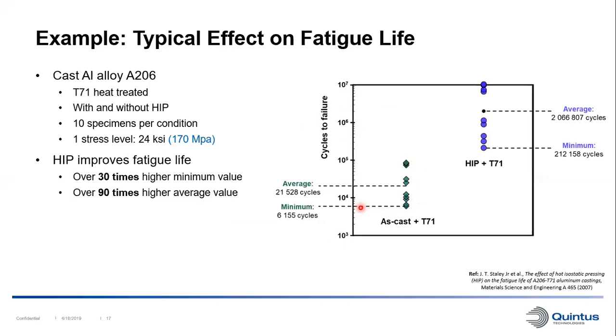Here we can see that the specimen that produced the minimum amount of cycles was around 6,000 cycles, and the average life was around 21 to 22,000 cycles. On the right here in blue, we have the same material that's been HIPed and then T71 treated. As we can see here, the minimum value is over 200,000 cycles, and the average life is around 2 million cycles. So here we can see that we get over 30 times higher minimum value with HIPing and over 90 times higher average value with the HIPed material. So this is one of the main reasons HIPing is used for castings.